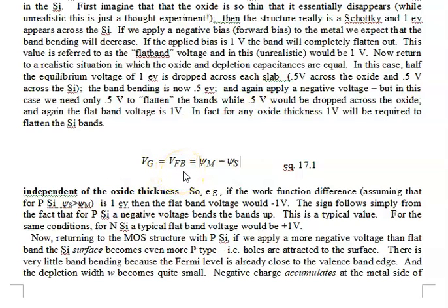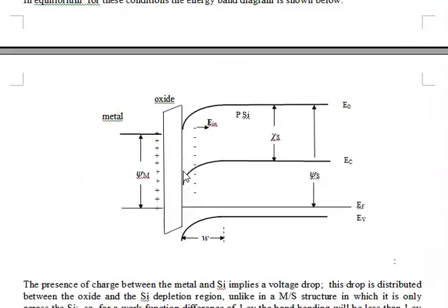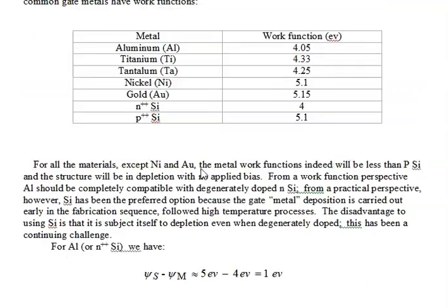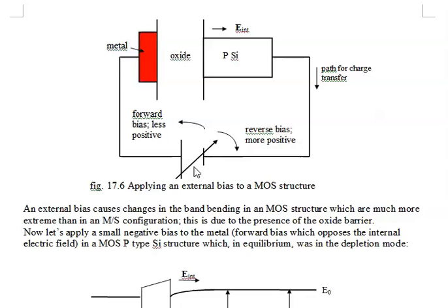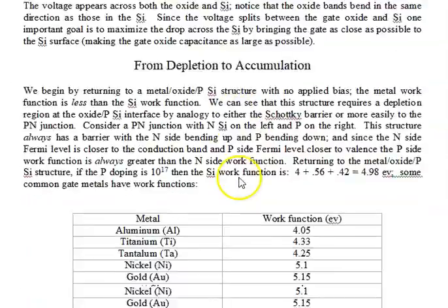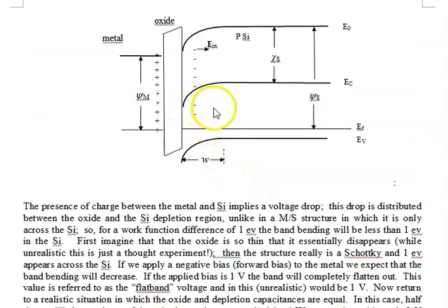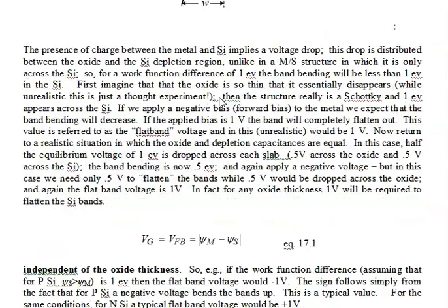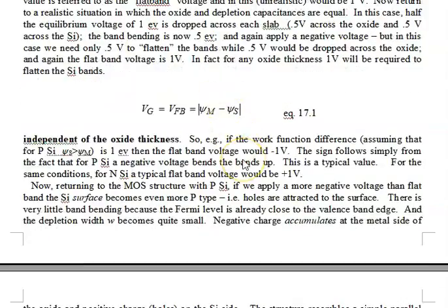Now what sense is that? Plus or minus in p-type silicon, which starts out in depletion? Well, we can go back right here. Forward bias, less positive, more negative. So I have to apply a voltage of minus 1 volt to go from the depletion condition where the work function difference is 1 volt. I apply a negative bias, and that would be a forward bias, and that gives me flat band.